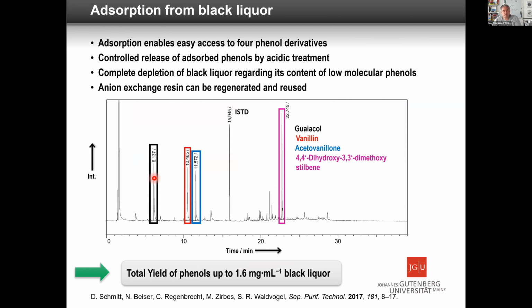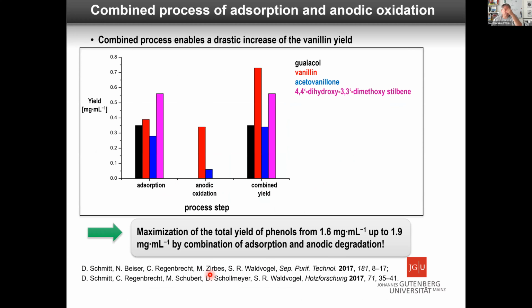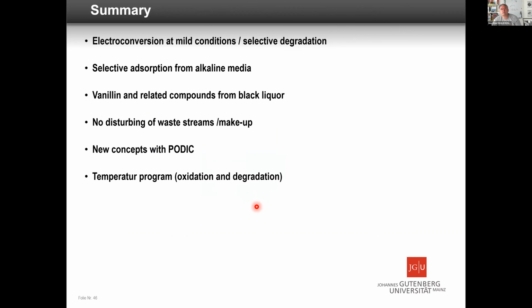Here you see these are the ones you can kick off the system. You have the internal standard. This is the guaiacol, vanillin, then acetovanillone. And there's something which you barely see in the black liquor, but this fits perfectly to the resin. And that's the reason why this enhances on that. This is a stilbene derivative, which can also be used as an advanced intermediate. Therefore, per milliliter, you get 1.6 milligrams of these phenols. Then you can rinse it off. You can take the black liquor, which is depleted of small molecular weight phenols, and electrolyze that, and then once more take it out. And therefore, you can combine these methods to enhance the amount of phenols.